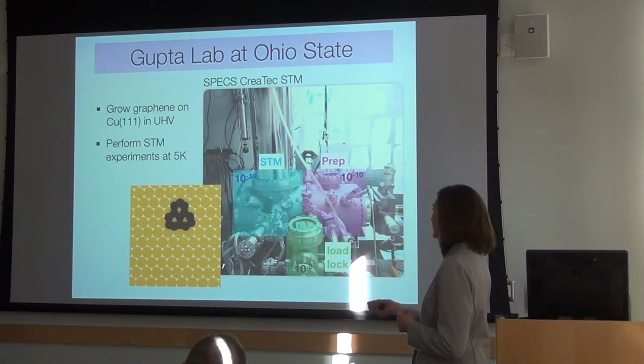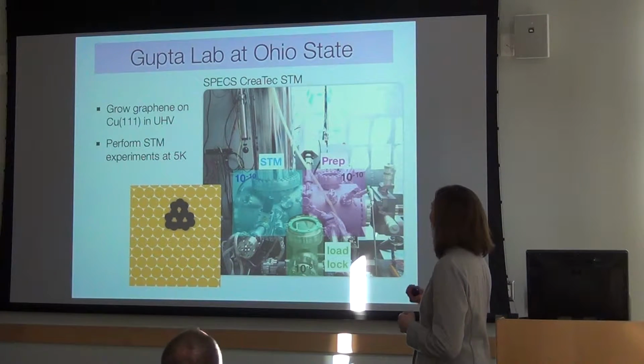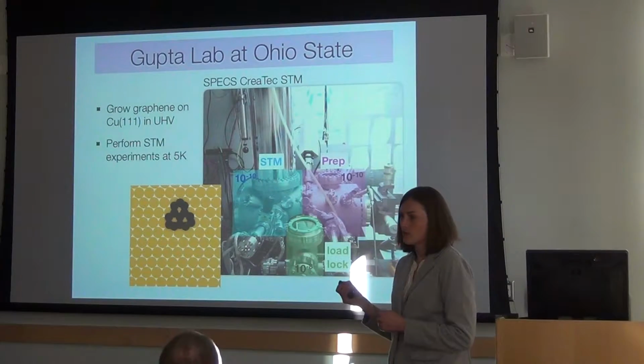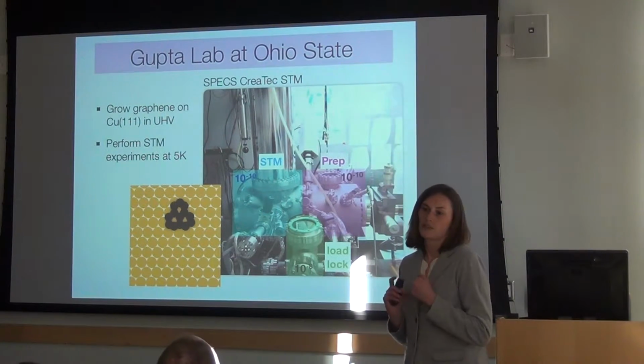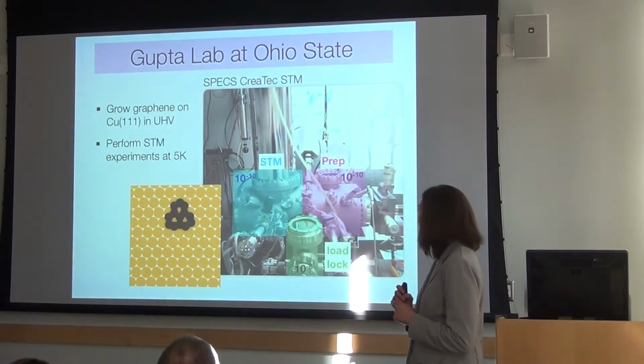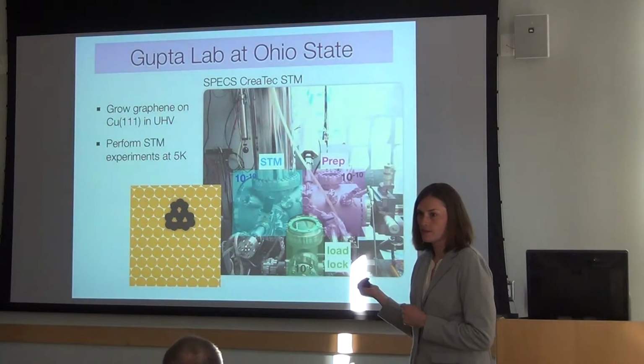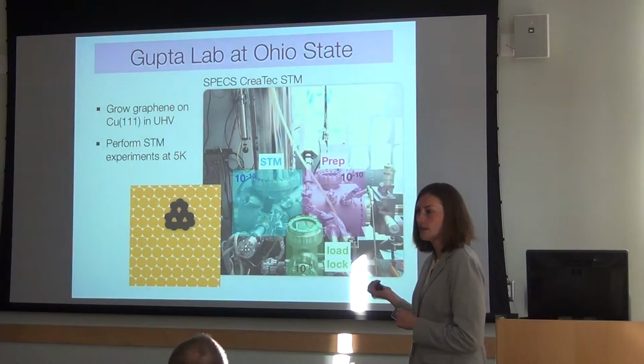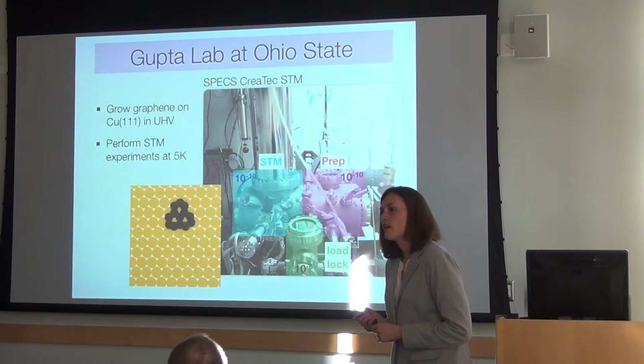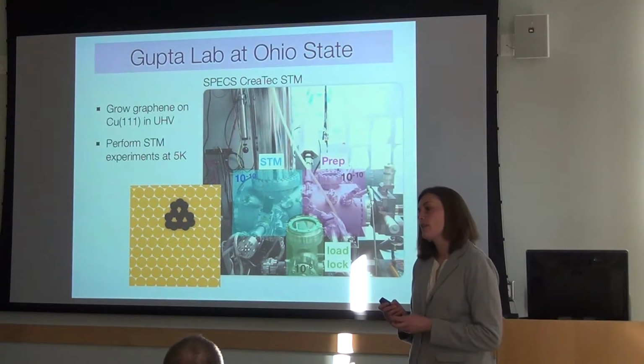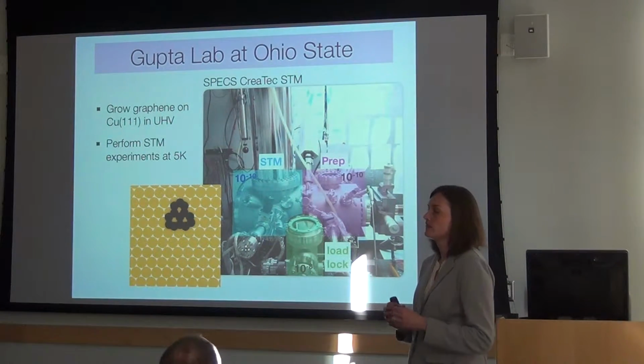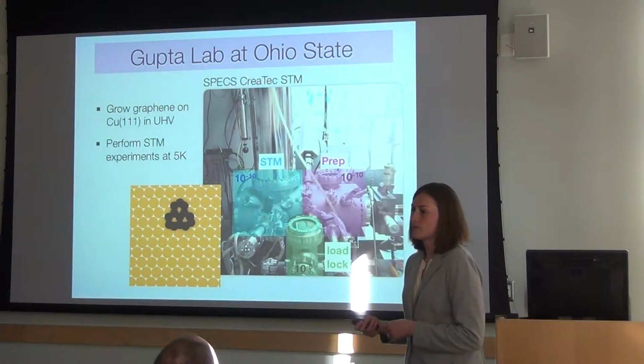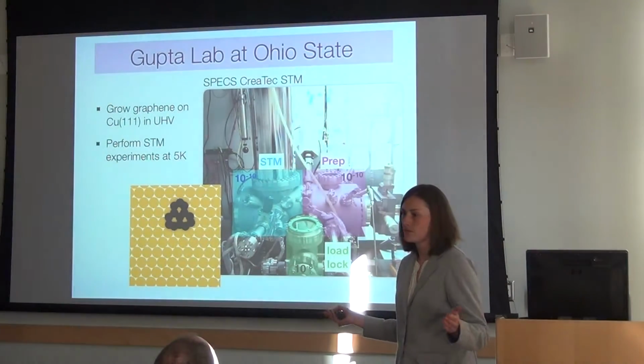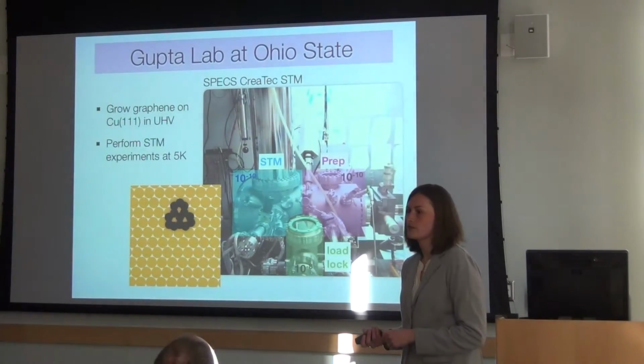And then we transfer this sample as quickly as possible from the prep chamber into the STM chamber, so that it stays really clean. We do that. Any questions about this? I'm probably not going to come back to this. Yeah. What's the size of the islands? I'll show you some images of islands. They vary in size quite a bit, from nanometers up to almost a micron.